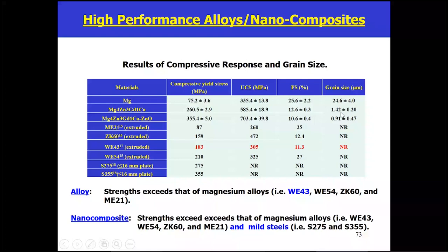Because these numbers exceed the properties of WE43 magnesium alloys, which FAA has approved for aerospace application. So you can use this material, which is much cheaper than WE43. If you put nano reinforcement like zinc oxide, now you look at the improvement in the yield strength by 100 megapascal, another 100 megapascal goes in the UCS, and your failure strain is compromised, but still more than 10%.